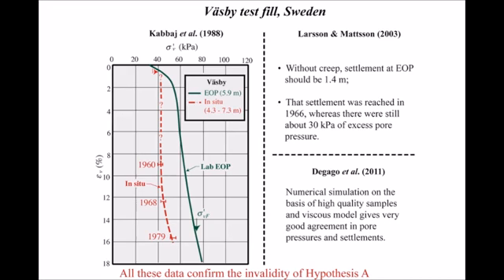We'll come back to the case of the Väsby test fill that I presented before, because we have there an explanation why there is this discussion between hypothesis A and hypothesis B. On the left, you have the figure I presented before, and you can see that there is a difference between the laboratory curve and the in situ curve of about 25 kPa.